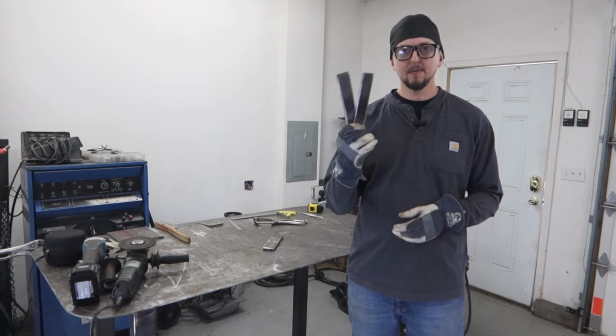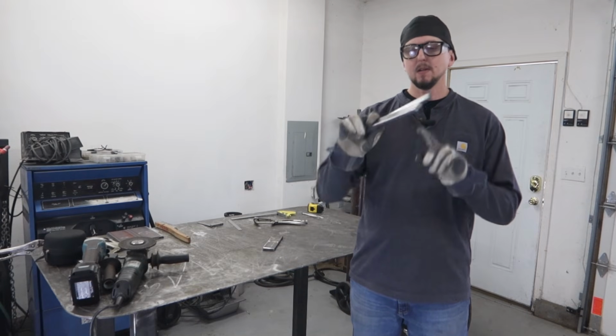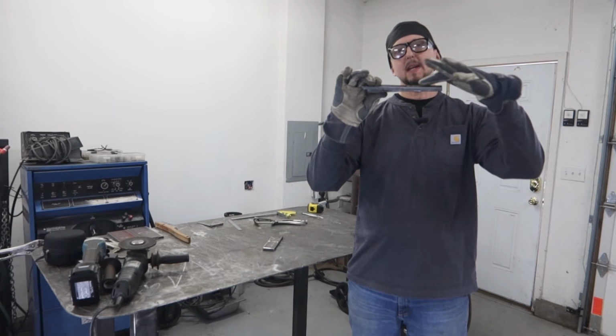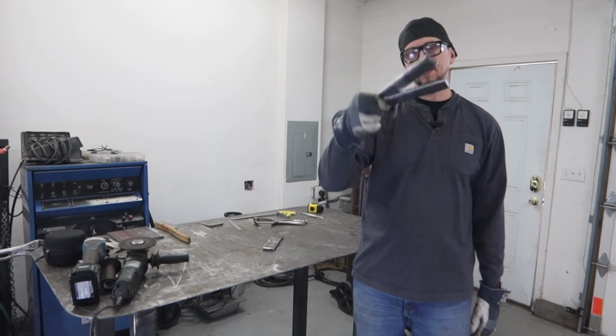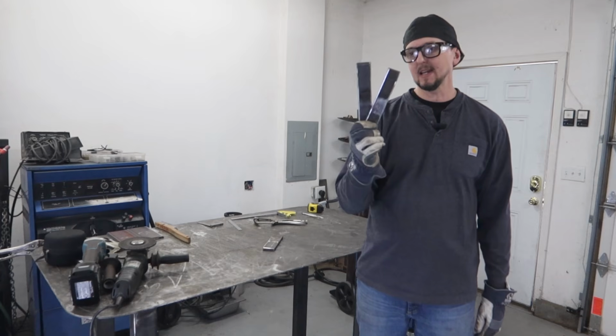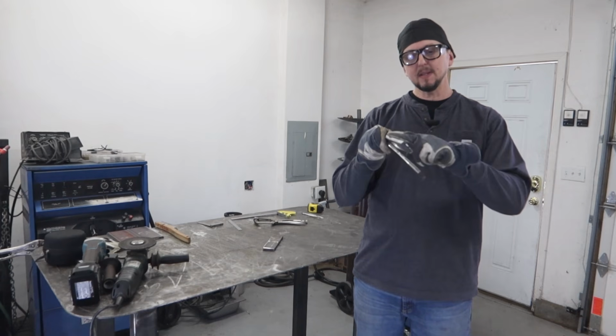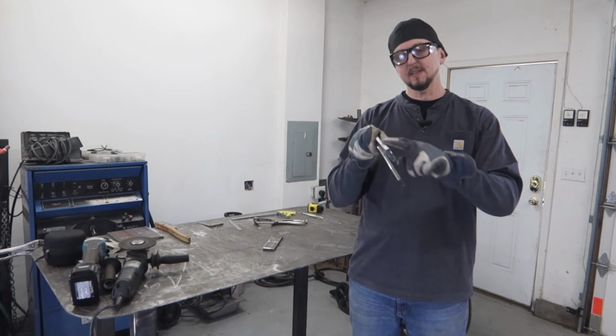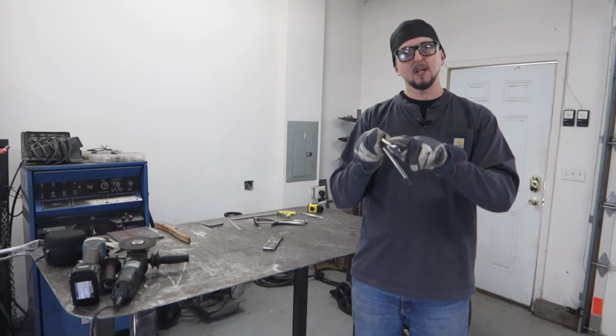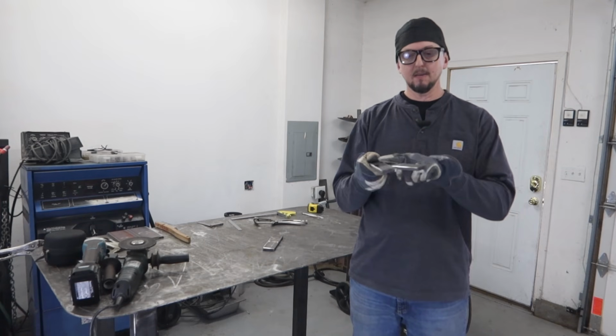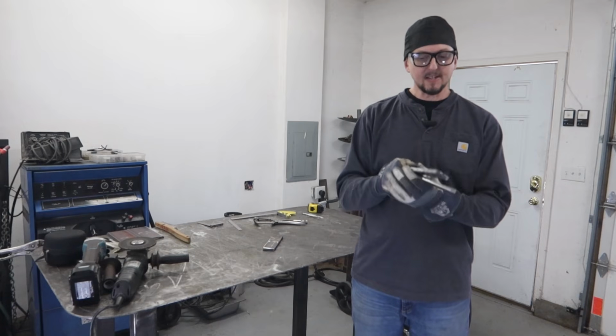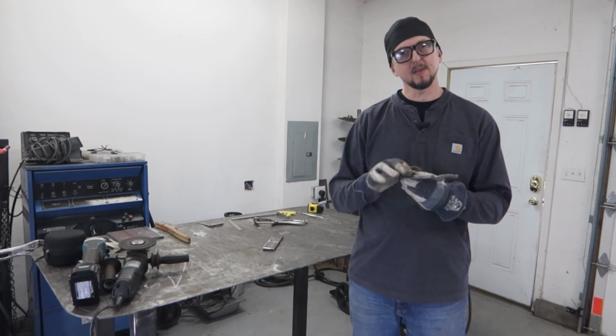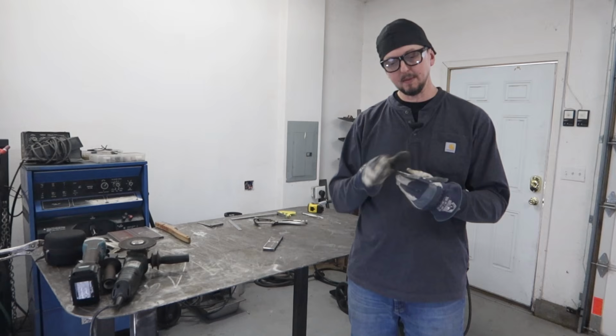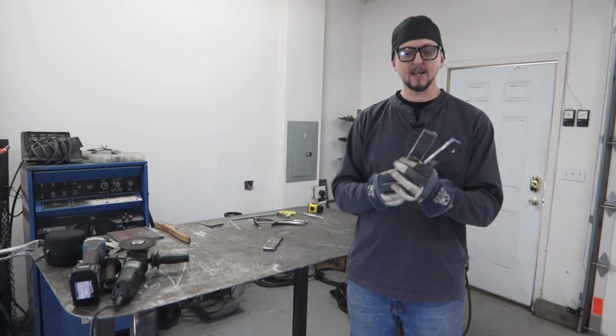All right, so now we have our pieces all prepped. So again, I've ground down till it's flush with the base surface on both sides, root and face side. And I've rounded the edges. So I broke the edges up to 1/8 of an inch radius on all the corners. And that's really important for our bend test so that we don't get corner cracks. So we want to make sure that we clean up those edges and break them.